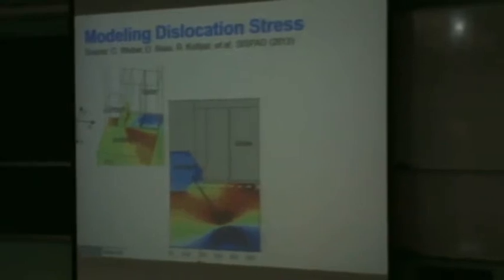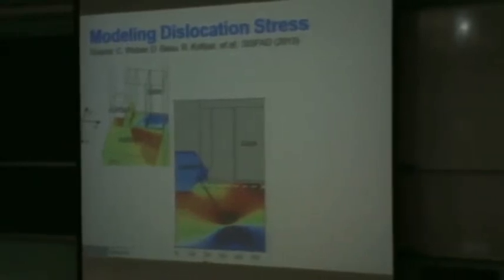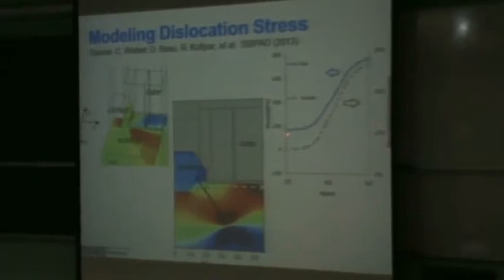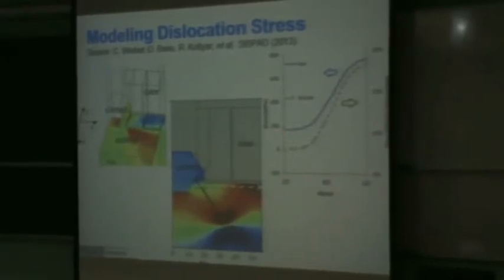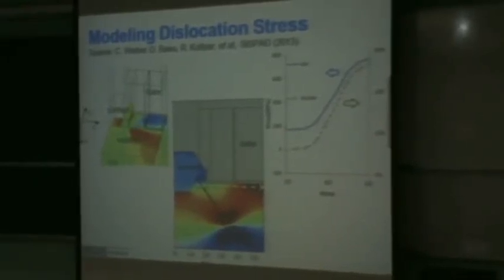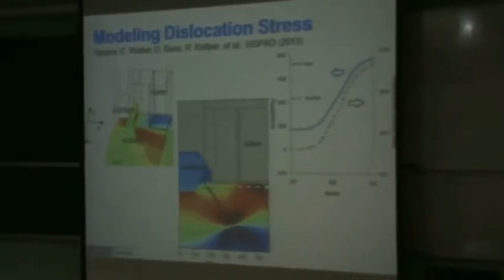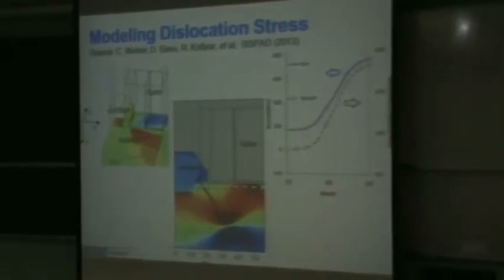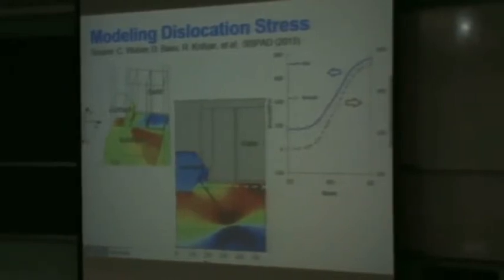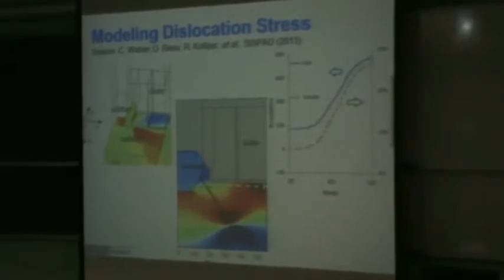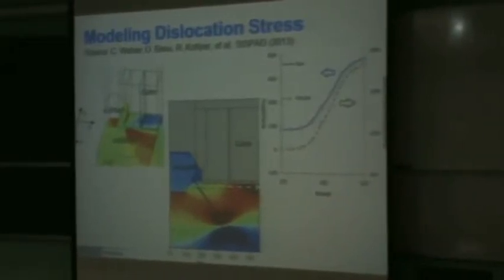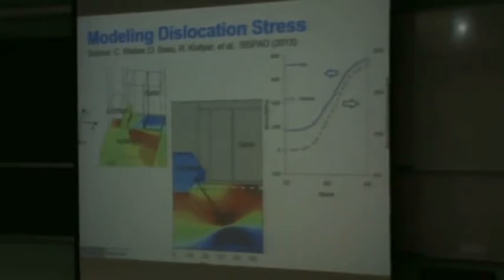If you take a slice right across the middle here, close to the surface, what you can see is a pretty healthy amount of stress. It's going from about 200 megapascals to about 700 megapascals. And again, what does stress do? It moves the positions of the atoms, in this case pulling them farther apart. You are changing the band structure, and it just so happens you change the band structure in a way that allows electrons to move a little bit more quickly through it. So you end up getting a mobility enhancement, and hence an on-current enhancement.